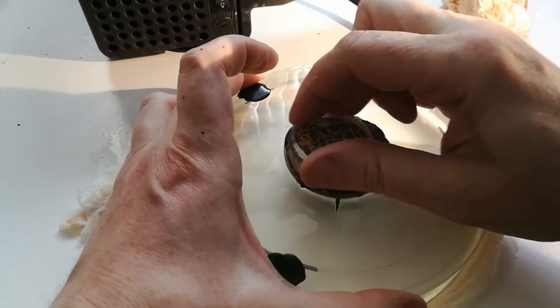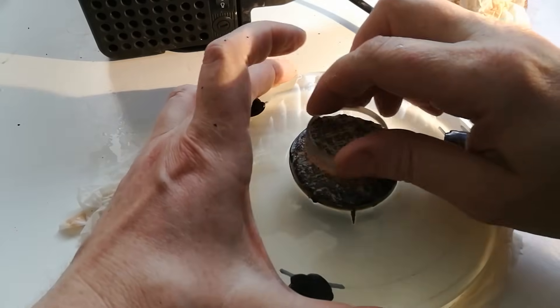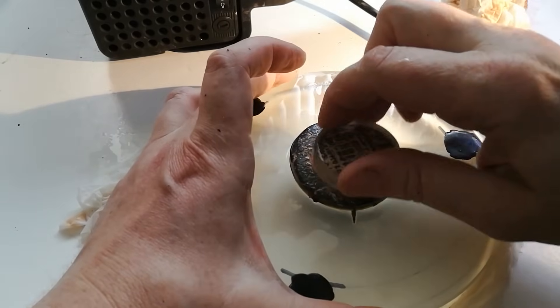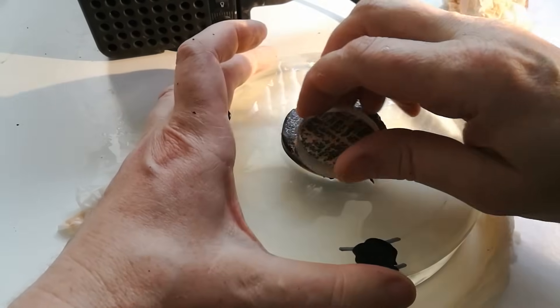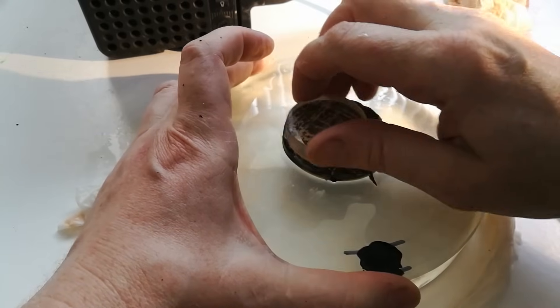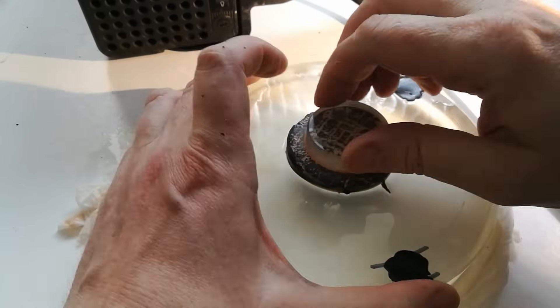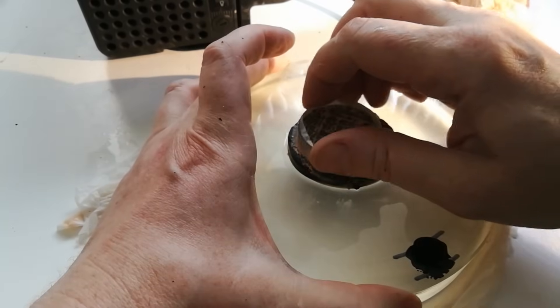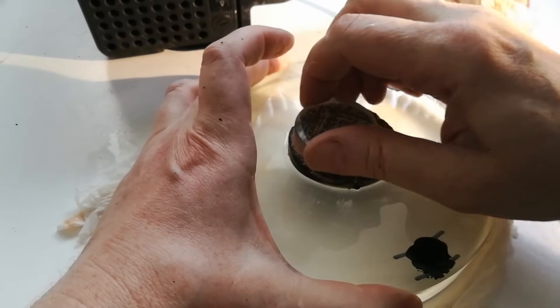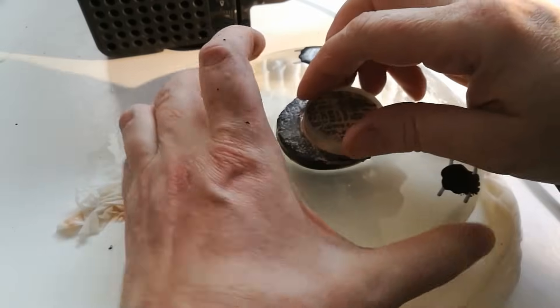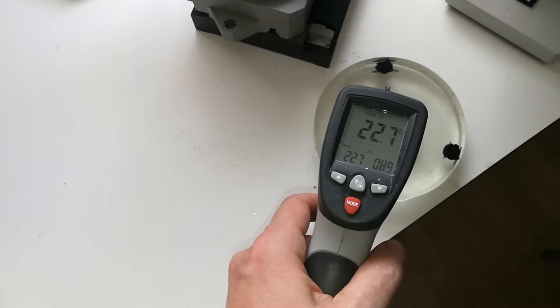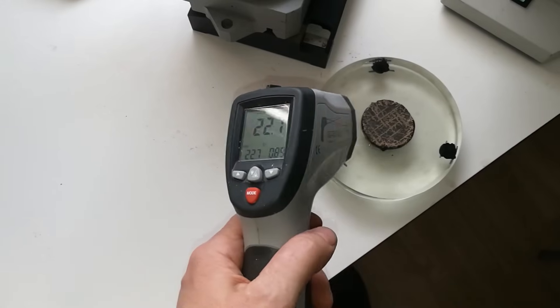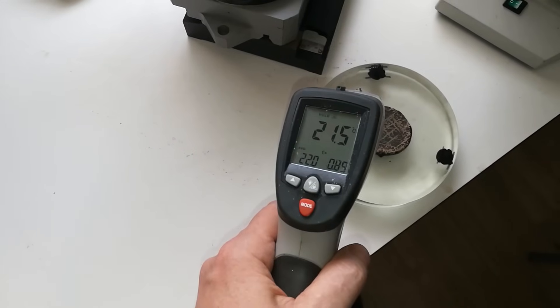It can be sped up using substantial pressure. However, using a high pressure will also cause a high friction and will lead to the generation of heat. This causes elevated pitch temperatures, which are undesired. So it is important to keep the pitch temperature constant and as close to its working temperature as possible.